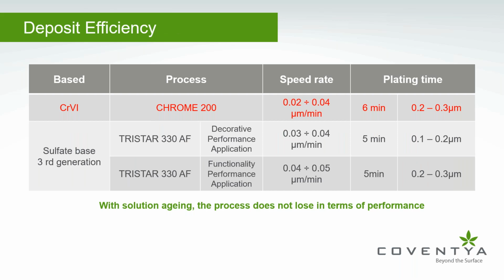We compare now the deposition efficiency of hexavalent chromium plating and Tristar 330AF. As you can see, with both versions, but mostly the functional one, the Tristar 330AF has higher plating rate. This allows the process to be installed without changing the position of the chromium plating tanks and the system cycle. In addition to that, the process does not lose in terms of performance.